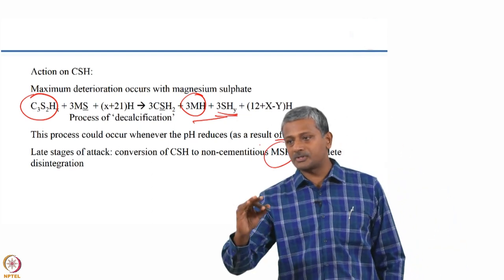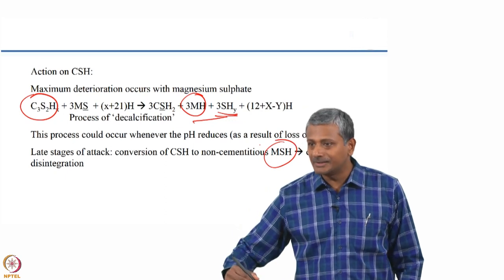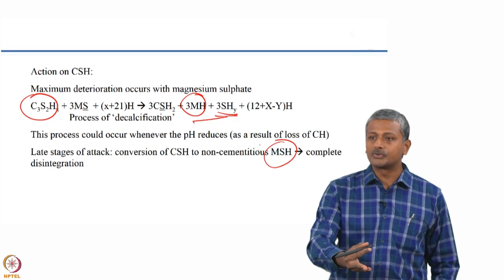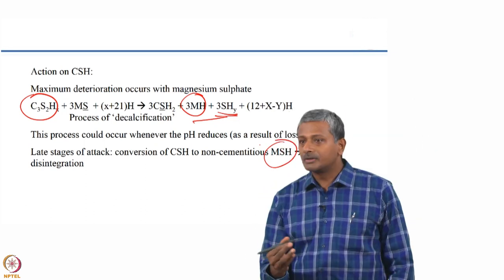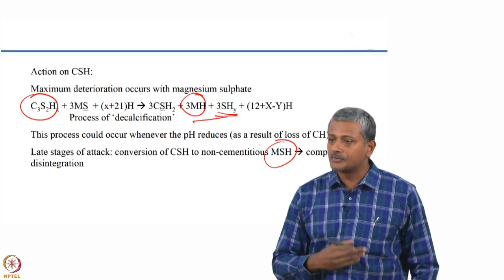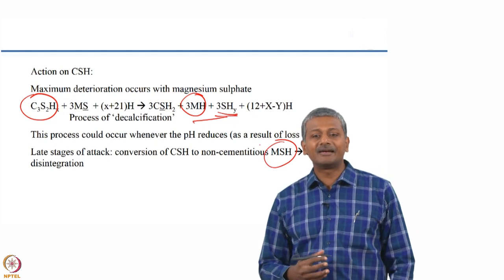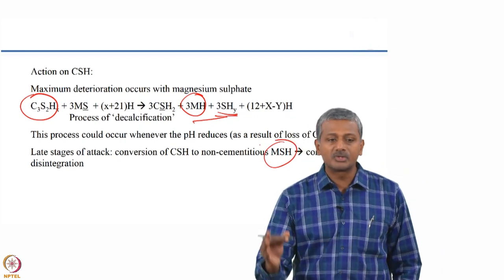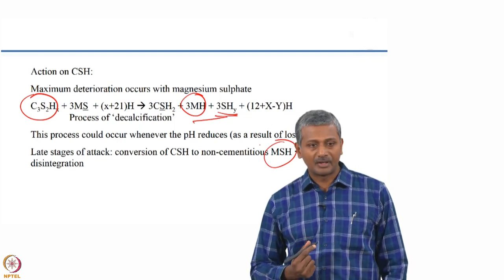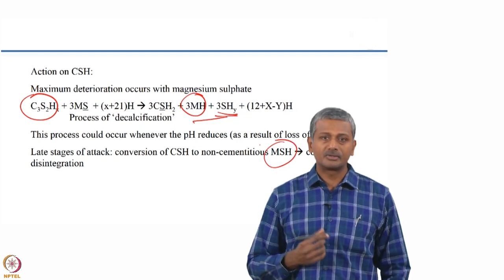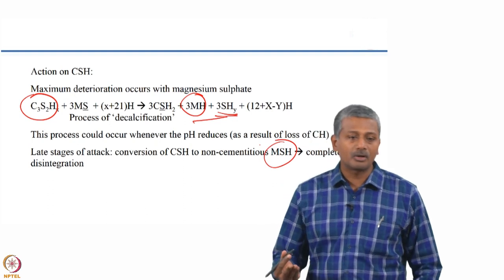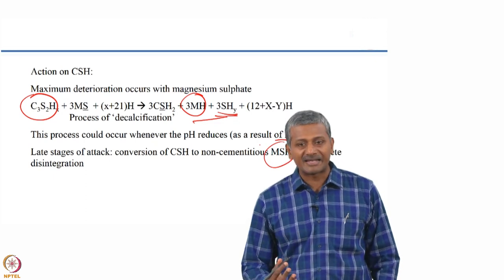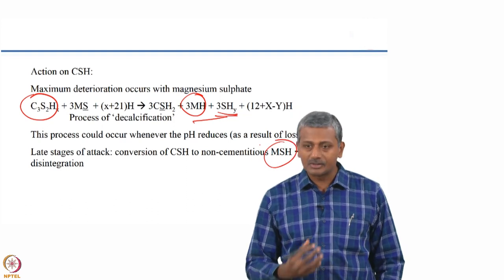So there are several stages: first, formation of gypsum; then formation of ettringite; and slowly but surely, decalcification of calcium silicate hydrate whenever an acidic condition is created around the CSH. If sulphuric acid is used instead of sodium or magnesium sulphate, the reaction will be all that much faster — you will form some gypsum, may or may not form ettringite (ettringite is not stable in a low pH environment), and the CSH will very soon start getting decalcified and the cementitious structure will be lost very fast. Interestingly, we use acid dissolution as a means of determining the amount of cement paste in concrete — the acid dissolution test — since siliceous aggregates do not dissolve in acid, whereas cement paste, being a calcium silicate hydrate, dissolves easily.